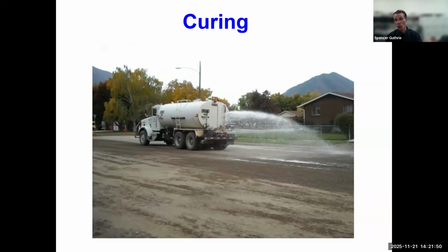And so we have to restore the water by bringing a water truck. Sometimes in Utah, where the measured relative humidity can be as low as 6%, and the wind picks up at night as the air is moving down from the canyons into our lower land, we might have to do this many times through the night just to keep it wet. There are alternatives. We realize we're also a desert environment and we don't like to use a lot of extra water. So if we need to, we can also just simply apply a prime coat, a bituminous seal coat, to the top of the cement treated base. And then we don't have to keep watering it, so to speak.